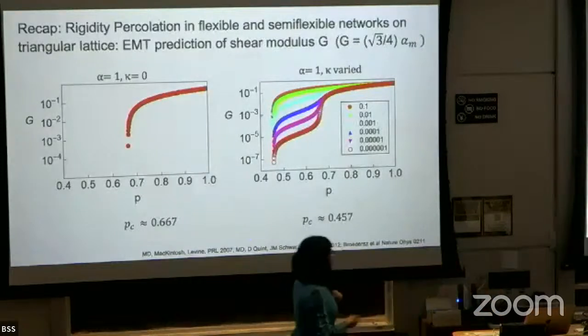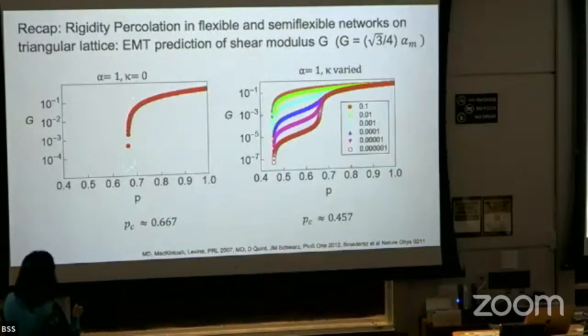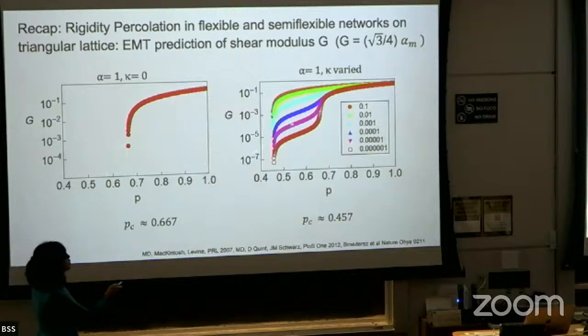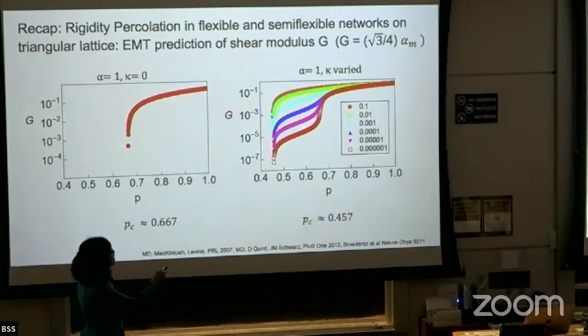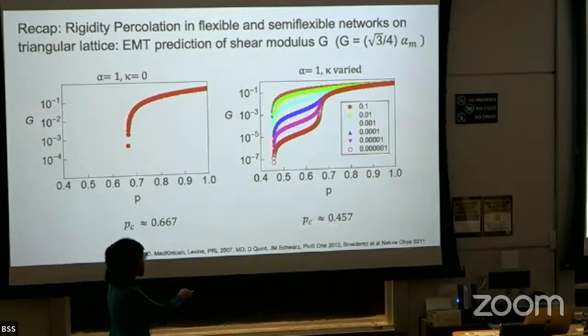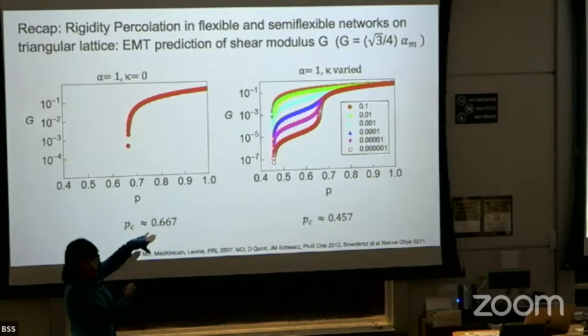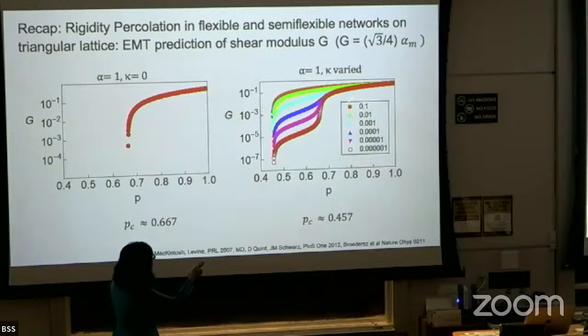And this is how the two things compare up, right? So if we did not have any bending rigidity, the percolation threshold is at 2/3, which I was talking about. But if we do have bending rigidity, then we have these extra constraints from bending. So the threshold moves to smaller value of P, and it's now like 0.457, right? And I had showed you how you get this 0.457. Because now, instead of just P equals 2/3, we have P plus P square equals 2/3, right, from effective medium theory. And this, I'm showing you what happens for different values of bending rigidity, right?